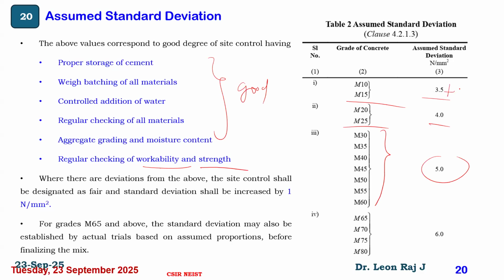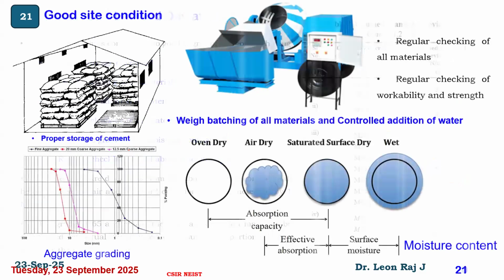If it is a fair site condition, you have to add 1 to each of these values. To come to a conclusion of good site condition, you should have proper storage, weighing of materials, controlled addition of water, regular checking of all materials, aggregate grading, and moisture content. So these are all essential. Proper storage of cement, fine aggregate, coarse aggregate. In coarse aggregate there are 10 mm aggregates and 20 mm aggregates. The gradation should be within the range. There is always a range, and it should come within that range. That's called aggregate grading: fine aggregate grading, coarse aggregate grading. Then there are 4 conditions: oven dry condition, air dry condition, saturated surface dry condition, and wet condition.